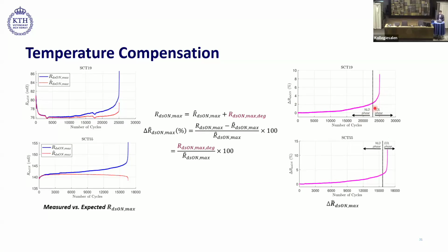So we divided this into two different phases, the NLD phase, which is also termed as near linear degradation phase, and EOL phase, which is also termed as end of life phase. What we wanted to do is that we want to compensate this linear increase due to drift in NLD phase, and then we wanted to see when the EOL phase starts occurring. So for this, we came out with the drift compensation method. First, we will go with method 1.